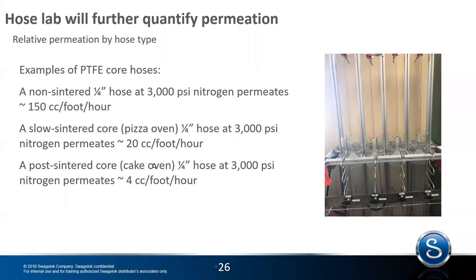Yes, thank you. Okay. All right, so if we do have a quarter inch non-sintered product, we find that it permeates at a rate that is significantly faster than anything we have that is sintered. There are two sintered methods that we apply. One is slow sintering, where we sinter the product, or heat it up, as it passes through the process. By slow sintering it, it's almost as though it's going through a pizza oven, where it goes in one end and continues to run through the other. And when it comes out the other end, it is finished with that process and the PTFE is tightened up.